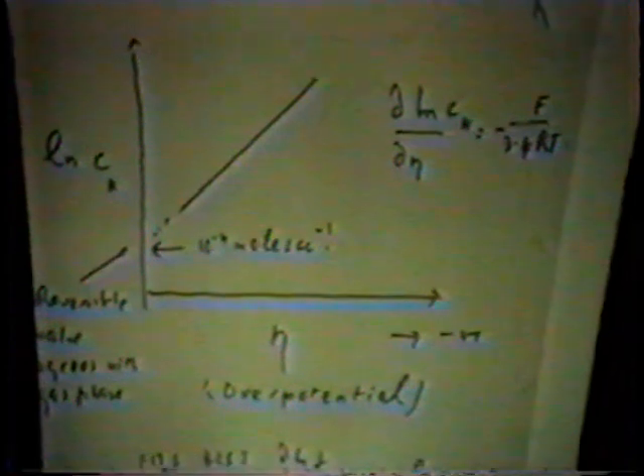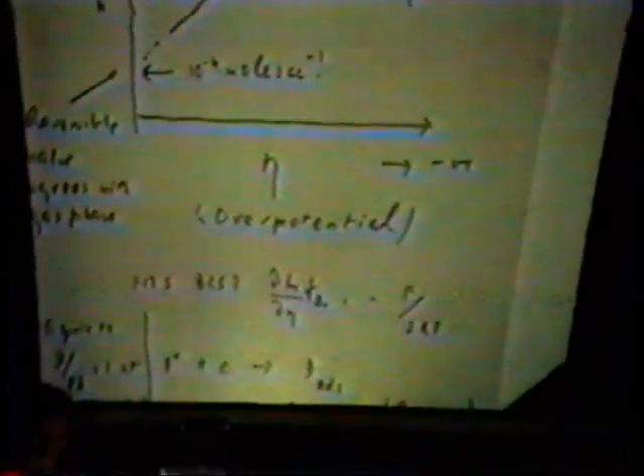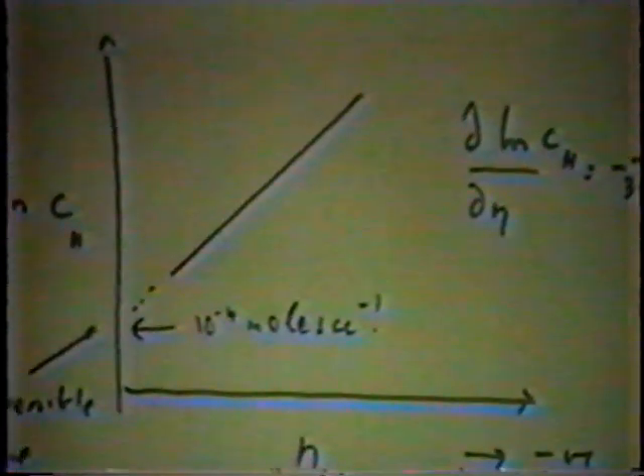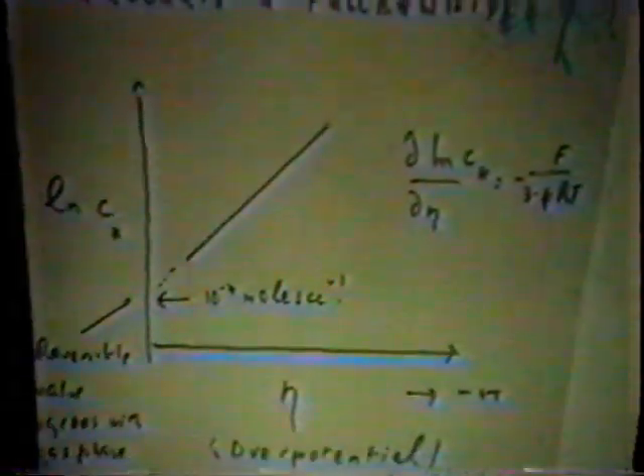Here's log of C_H, that's the atomic concentration of hydrogen in palladium. This is the overpotential. It extrapolates at zero potential to 10 to the minus 4 moles per liter, moles per cc. And that's a very verifiable figure, because of course you can just take palladium and have hydrogen gas around at 1 atmosphere, and that should give you the same value as the extrapolated electrochemical value that you're getting by finding the permeation value of the hydrogen through palladium and so on. So you've got to check on it. It comes out to about 80% right. It's not an exact verification.